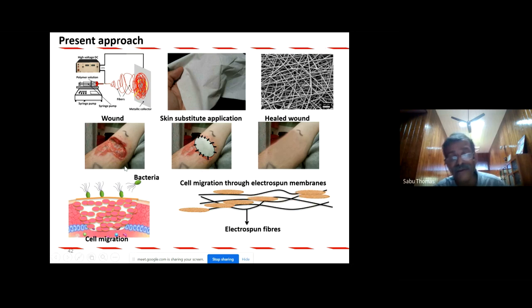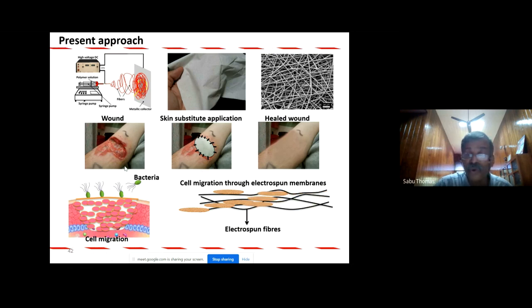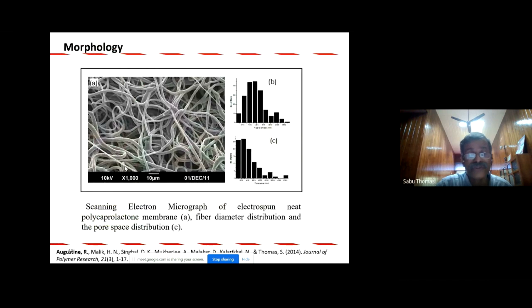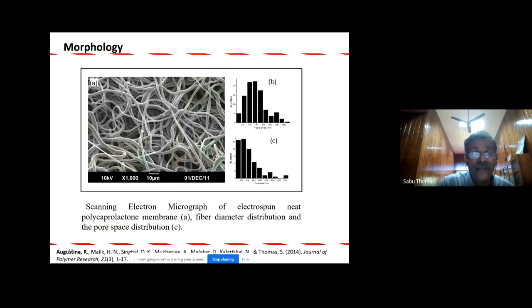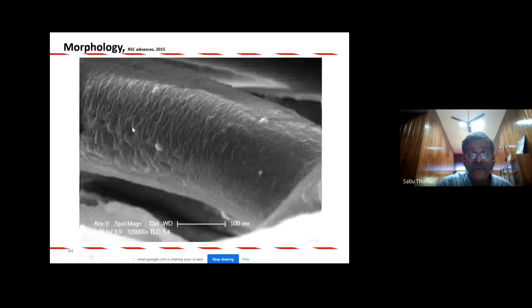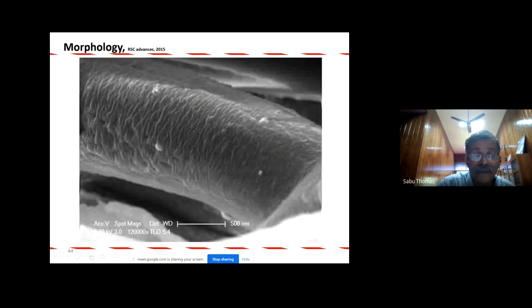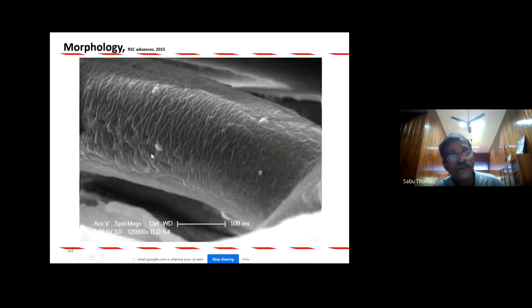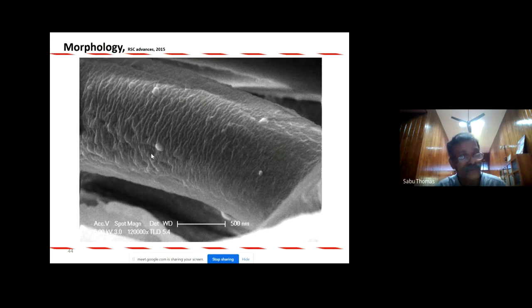And you can see cell migration, cell proliferation, angiogenesis is quite high when you use this. This is actually the picture of our electrospun system. And we also introduce nanoparticles. See, this is nanoparticles of zinc oxide. Very small amount of zinc oxide, less than 1%. The size is 50 to 60 nanometer size.